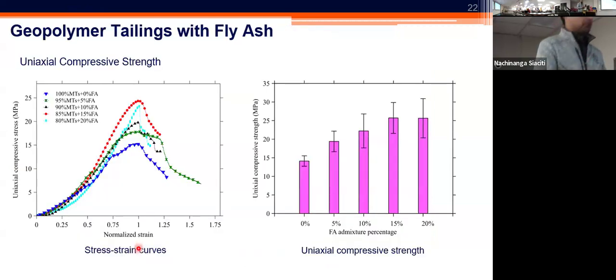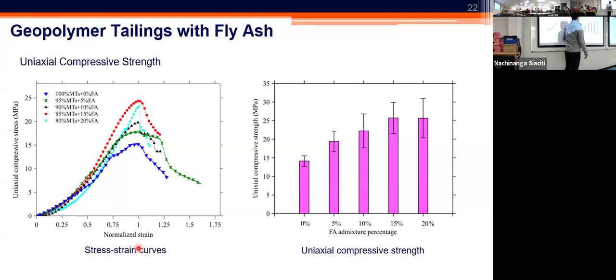In terms of the influence of the fly ash addition, we documented that when the samples are tested, if we consider the control with 0 amount of fly ash, we see a favorable improvement in the strength and the general stiffness of these samples, if you look at them in terms of the relationship between the stress and the strain. But looking at the peak values and plotting them as a function of the addition of the fly ash, you can see here that with the addition of the fly ash, we generally have an improvement in the compressive strength of these samples.